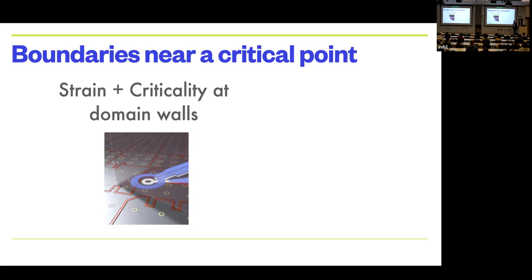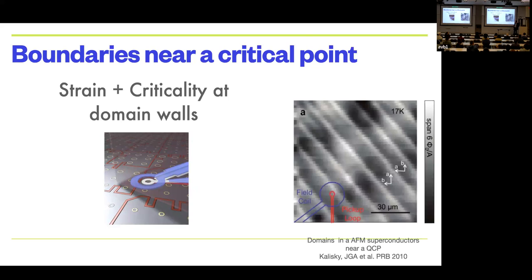There was a measurement that we did in these systems when they were superconducting called scanning SQUID. For those of you who don't know, it's another way to measure the local magnetism in a system, but with very high resolution. You basically have a little magnetometer that goes across the material, and you can measure what the magnetism is. But you can also measure what the superconductivity is doing through the same kind of signal, just in the opposite direction. And so we worked with Kam Moler at Stanford and her postdoc at the time, Beena Kalisky, who's now a professor at Bar-Ilan University. And they came up with this image of what the superconductivity looked like. This probably should look familiar by this stage in terms of the other images that I was showing you. They're just the domain walls of the orthorhombic crystal, of this broken symmetry crystal.